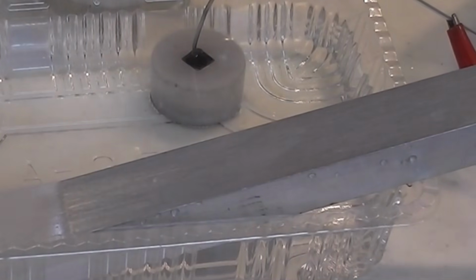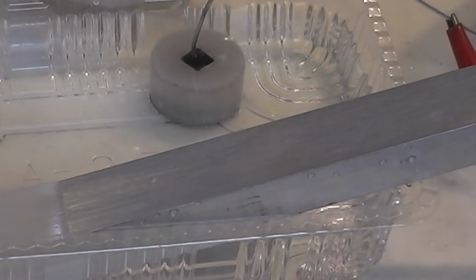While the oxide layer is forming, another reaction is taking place. Oxygen gas is continuously released from the surface of the aluminium. Those tiny bubbles may seem harmless, but they can create a problem. If a bubble stays attached to the surface, it blocks the electrolyte from touching that area of the aluminium. Where the electrolyte cannot reach, the oxide layer cannot grow properly. That means the dye won't be absorbed evenly later in the process. We'll see the effect of that in just a moment.